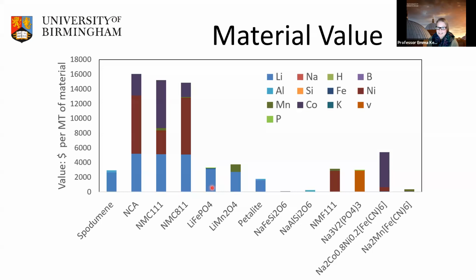If we look at lithium iron phosphate, again, the lithium content of lithium iron phosphate is quite high. It's slightly higher than the spodumene. And so there must be value for reclaiming the lithium from this material. However, the iron and the phosphate that you can see here, for example, is very low. So maybe the value for that is slightly lower. If we now look at similar sodium materials, this is a Prussian blue analog here with manganese and iron. This one has nickel and cobalt in, so it's got a higher value slightly. This is the vanadium one, and this is the nickel type material here. But you can see the value for these is significantly lower.